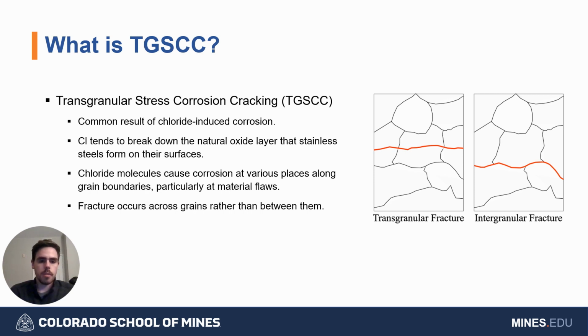Because of this, when chloride molecules interact with grain boundaries, they start to corrode at certain points along the grain boundaries, particularly at flaws that already exist in the crystalline structures. This promotes transgranular cracking rather than intergranular cracking, so the individual metal grains fracture themselves rather than just splitting apart.